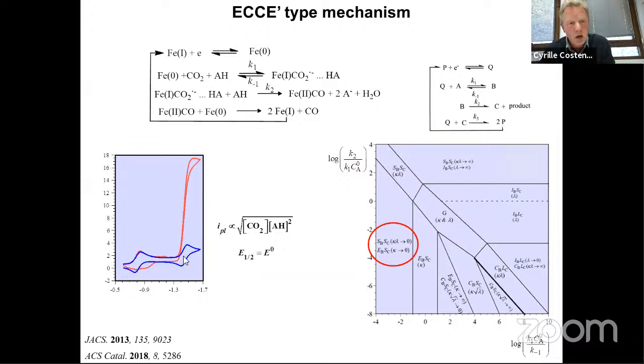One from the plateau and one from the fact that, as you can see here, the half-wave potential is exactly equal to the standard potential, which means that the first irreversible chemical sequence is the rate determining sequence. And so what you get from the plateau is the overall constant for this pre-equilibrium times this irreversible rate constant, okay? And of course, the reason why you go from a reaction order of 2 in acid to